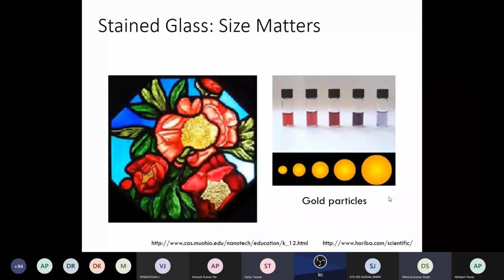So before coming to SEM, TEM or XRD, you can ensure whether you have successfully synthesized in a certain range or not by UV visible absorption spectroscopy, because materials of different shape and size will absorb at particular wavelengths. Spherical gold nanoparticles of about 50 nanometer will come at a 550 nanometer absorption peak in UV. And if the size is smaller, from 50 to 20, that 550 nanometer peak can shift to a lower wavelength like 500 nanometer.